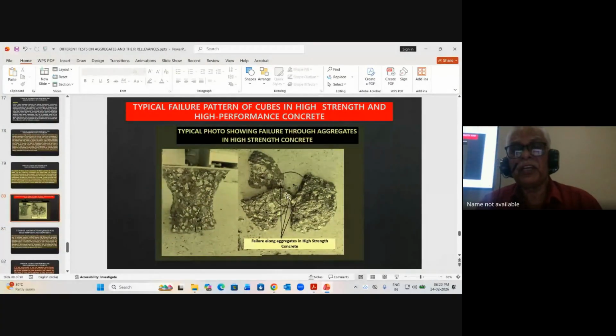See, this is where I have taken a sample for high performance concrete. You can see here the aggregate, breaking is taking place in the aggregate. In high performance concrete, the failure should take place through the aggregate, not through cement mortar. But in normal concrete, we allow breaking through cement, not through aggregate. You can see here how it is breaking through aggregates in high performance concrete. It's very, very interesting, so you can also do some experiments at site and think about it.